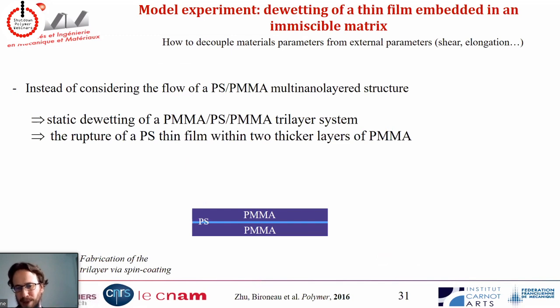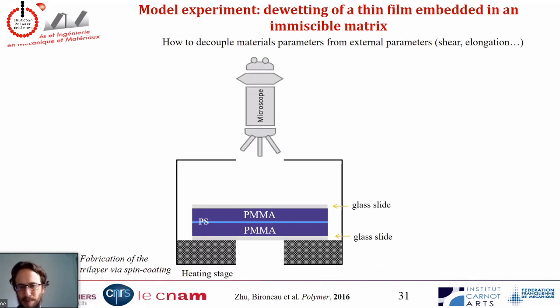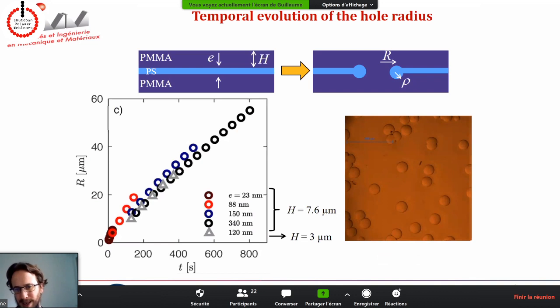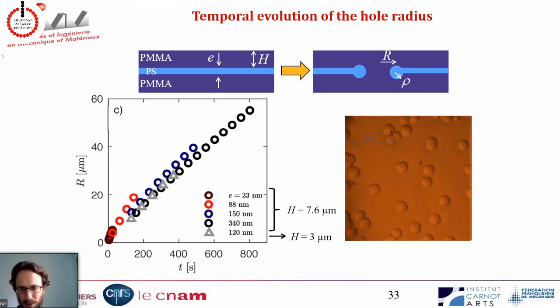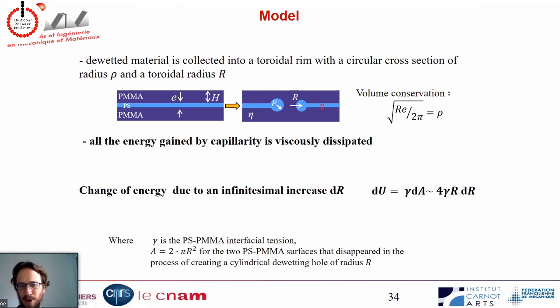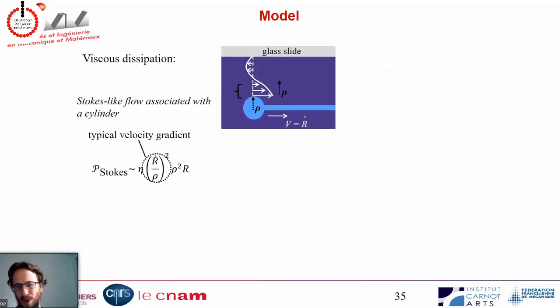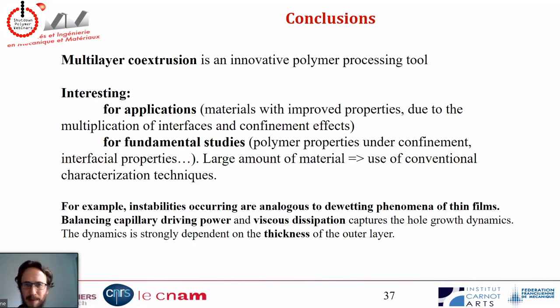But what we did was try to build model experiments to confirm this hypothesis, because at this stage it's only a hypothesis. So we designed dewetting experiments to try to confirm what happened in the polymer co-extrusion process. We designed an experiment where you can check the dewetting, and then we designed a simple model that I'm not going to talk about now, but that allows us to model the dewetting of our thin films.